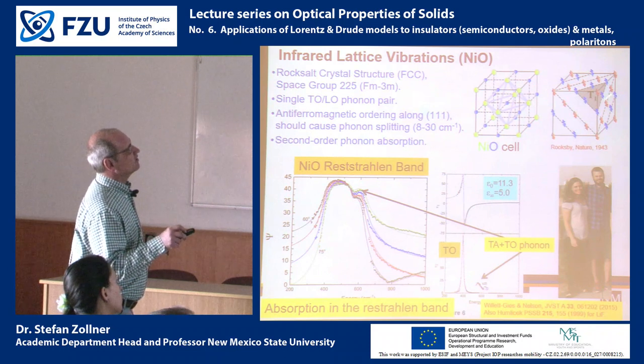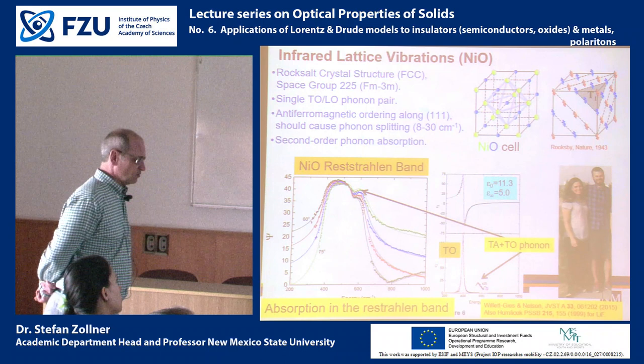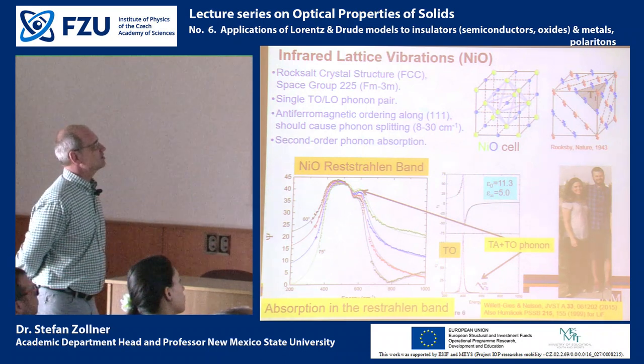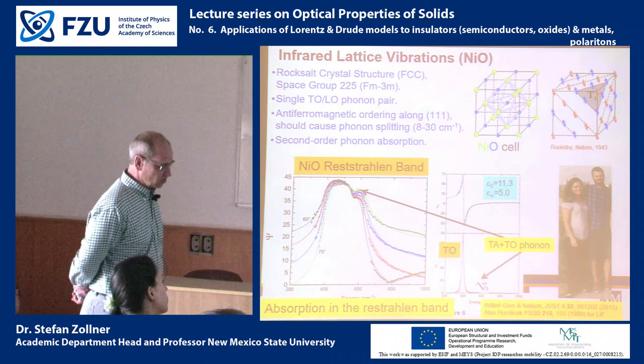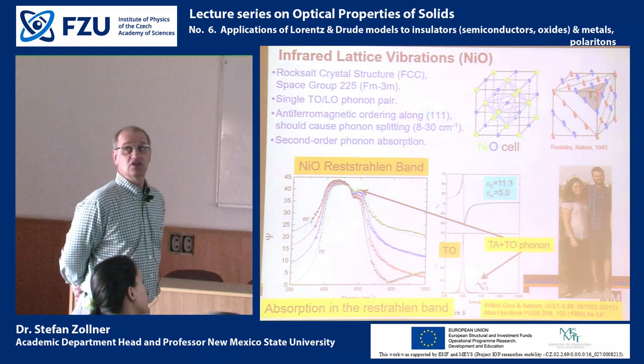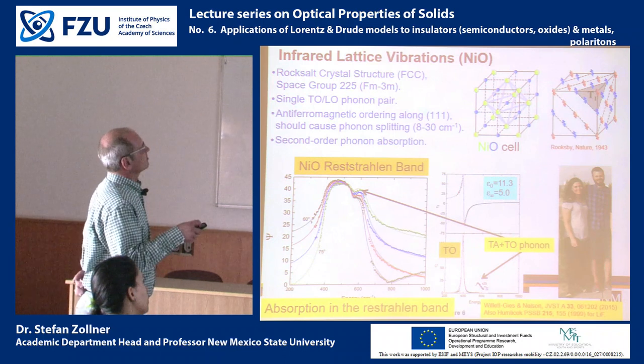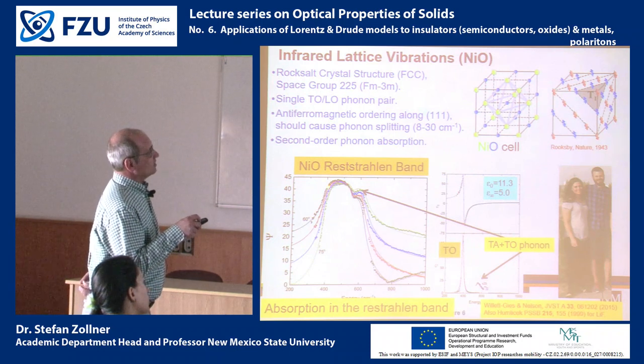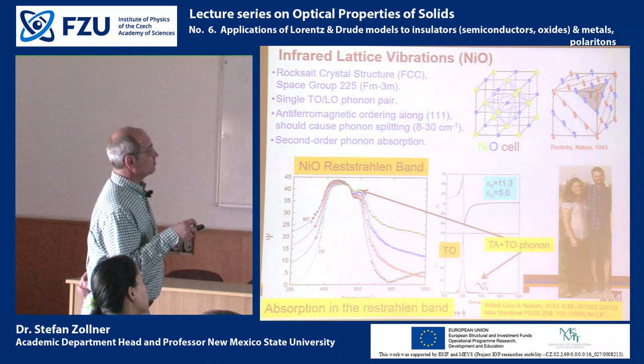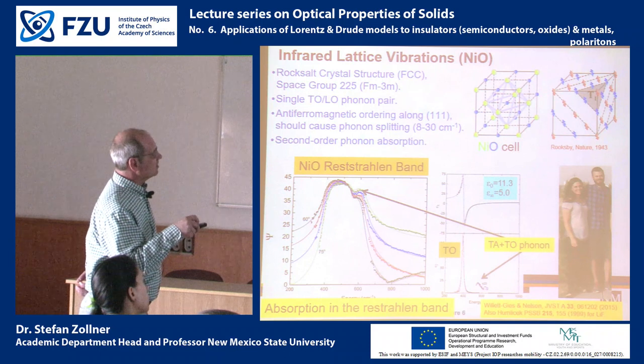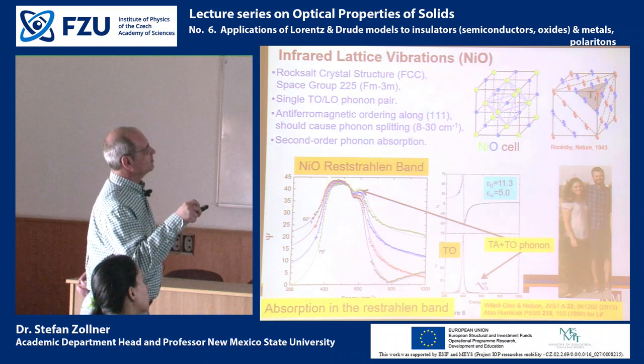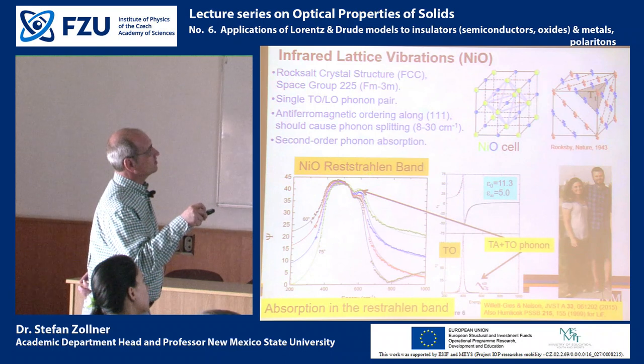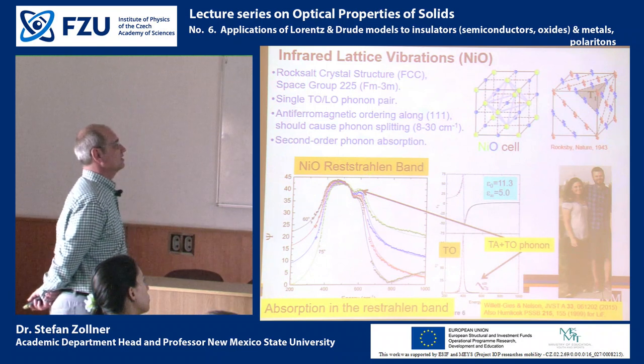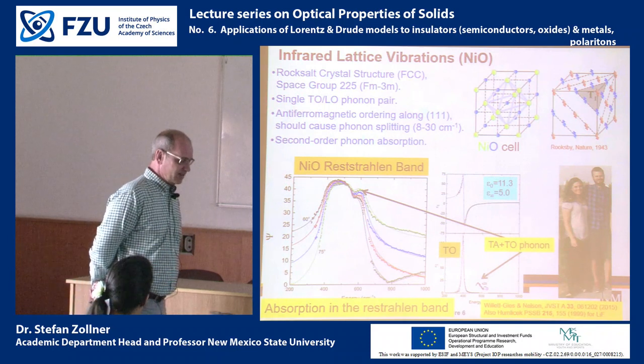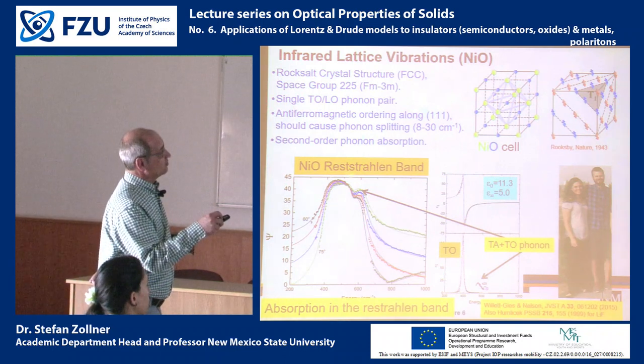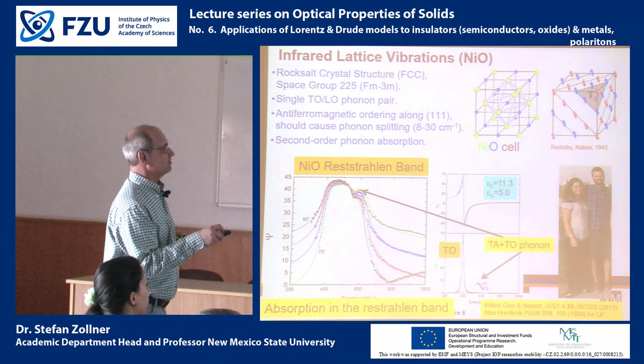And there's this magnetic ordering along the 1-1-1 direction, and because of that, there is a very small orthorhombic distortion of the nickel oxide crystal structure. So when we look at the Reststrahlen band, we clearly see there's something wrong, because we should see an increase of the reflectivity at the TO frequency, and then it should stay constant, and then there should be another drop in the reflectivity at the LO frequency. But here we have one drop first, and then there's a terrace, and then there's another drop.